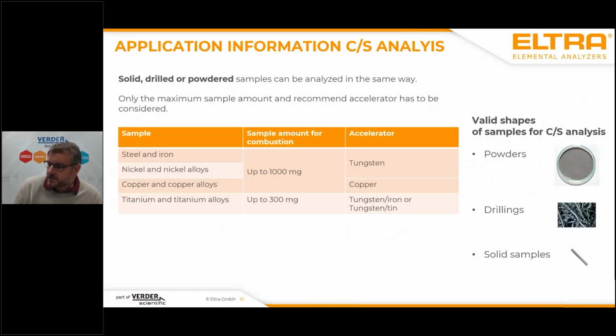The basic things which are important for carbon sulfur analysis with ELTRA are the general application settings. We are free to analyze every form of sample, which means you can apply powder, drillings, chips, granule samples, or solid samples in any shape. This is a big advantage of this technique. When you are used, for example, to performing measurements with optical emission spectroscopy, you usually have to provide a special sample shape, or maybe you have to take your sample and disintegrate it in acid. But for combustion analysis, it's very easy. You just take your sample, put it in the crucible, and then apply your accelerator.